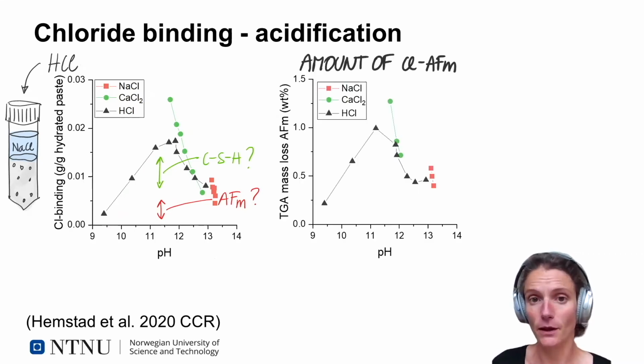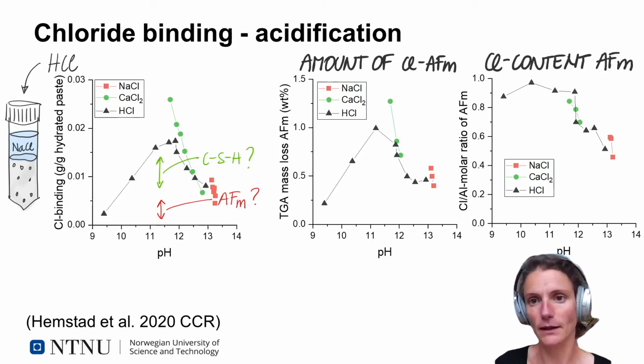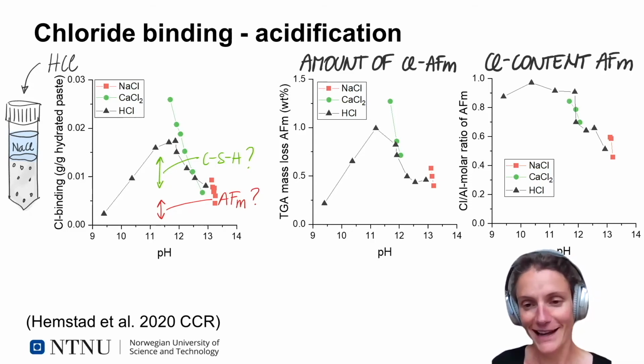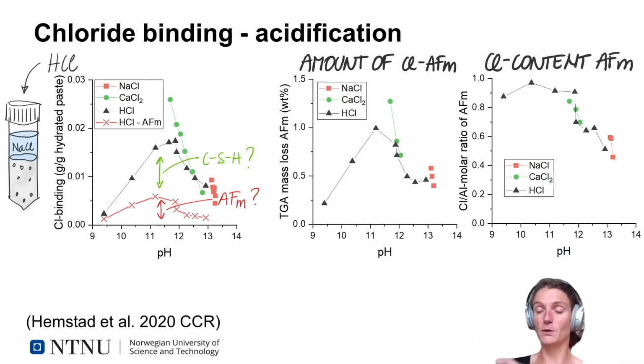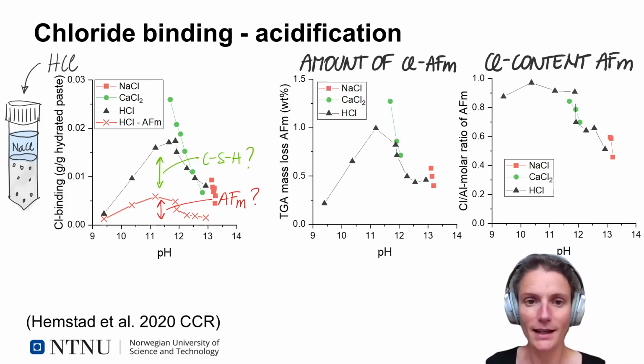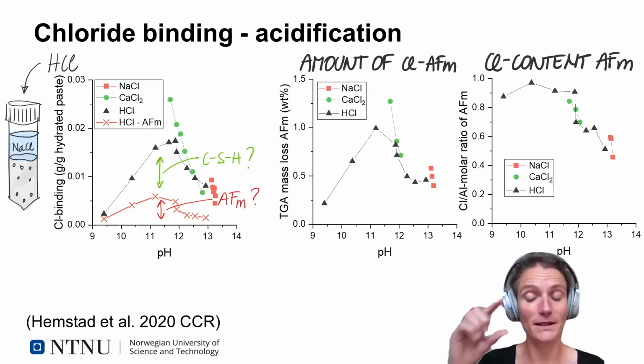Peter determined the amount of chloride AFM using TGA, and he determined the chloride content of the AFM using SEM-EDS. And we can see that the amount of chloride AFM actually follows a bit the trend of the binding isotherm. And we also see an increase in the chloride uptake of the AFM when we're decreasing the pH. So if we combine those two, we can see that the AFM is contributing to this peaking behavior you see in the chloride binding, but it's not explaining the whole thing. So again, our hypothesis is that the part we can't account for might be due to CSH.